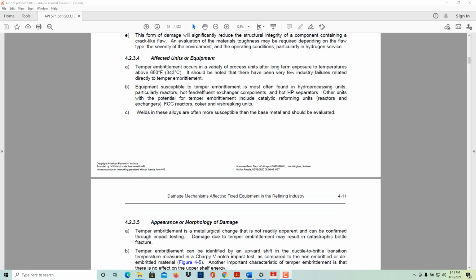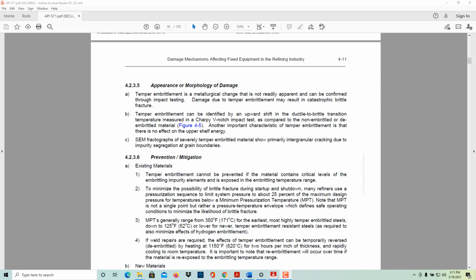Affected units or equipment. Temper embrittlement occurs in a variety of process units after long-term exposure to temperatures above 650F. It should be noted that there have been very few industry failures related directly to temper embrittlement. Equipment susceptible to temper embrittlement is often found in hydroprocessing units, particularly reactors, hot feed effluent exchanger components, and hot HP separators. Other units with the potential for temper embrittlement include catalytic reforming units, reactors and exchangers, FCC reactors, coker, and visbreaking units. Welds in these alloys are often more susceptible than base metal and should be evaluated.